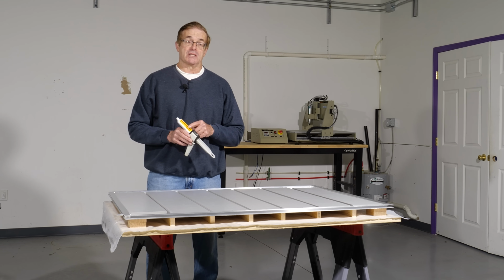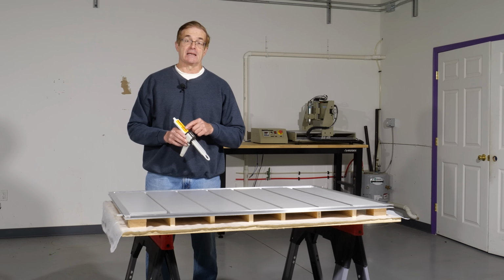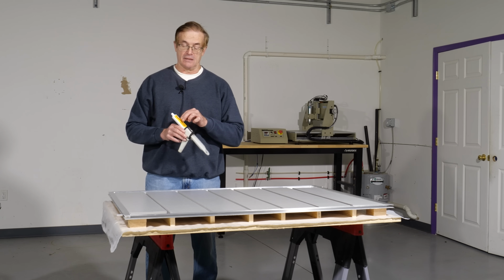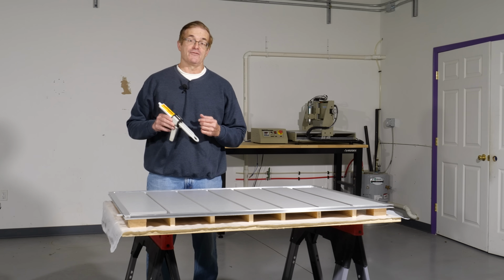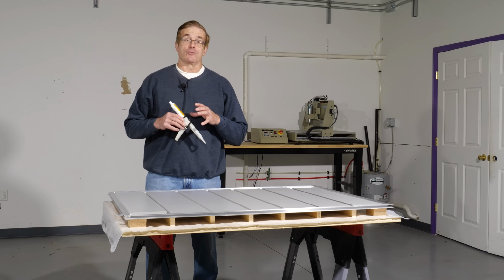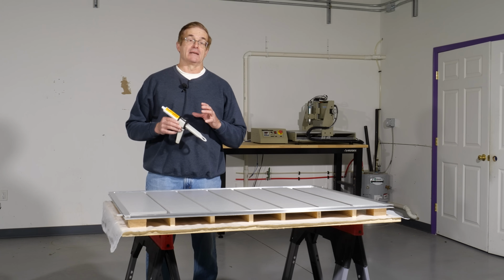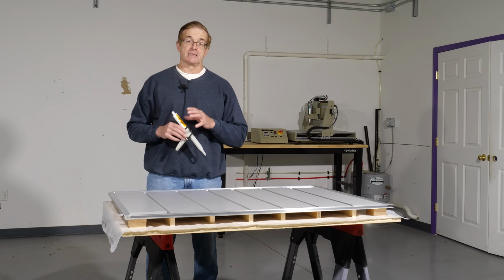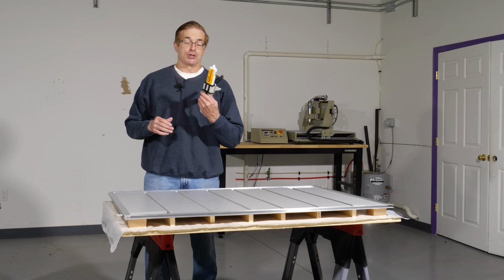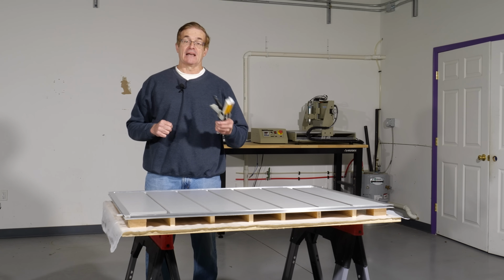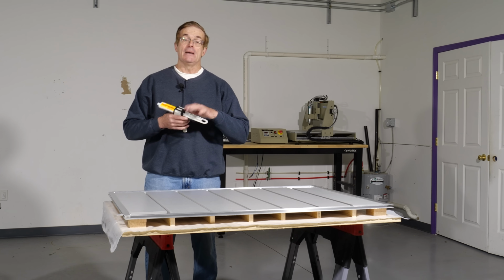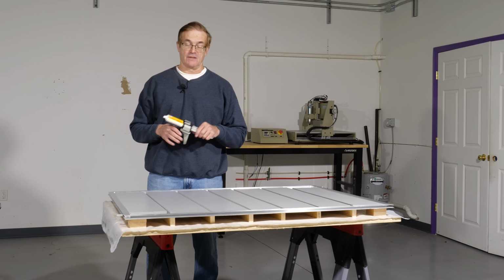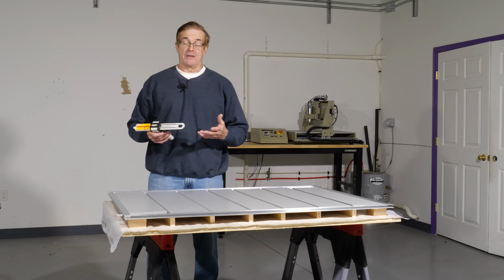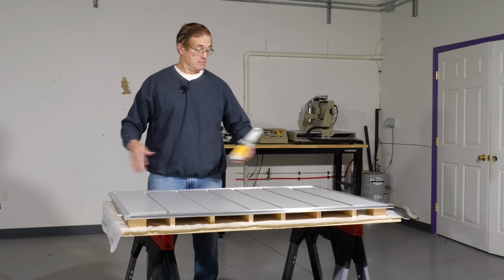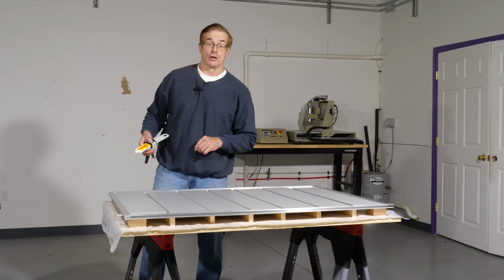And this particular material is also useful because it has some rubber powder in the mix that makes this a toughened epoxy. So it's much more resilient and flexible and will not crack as easily as the pure epoxy resin. It's also super for bonding surfaces that have different coefficients of thermal expansion, like glass to metal, because it can take up some of that differential expansion. So with that, I'm going to start by putting on some gloves, and we're going to get this thing going.